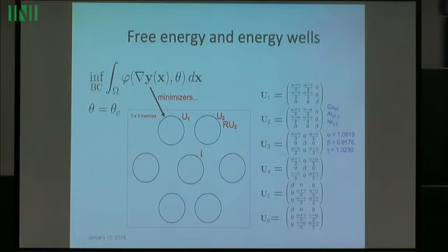And there's also rotational invariance, so that's what the circle denotes. So U2 in fact is also a minimizer, an equi-minimizer with the identity of phi, and the circle just represents all rotation matrices times U2. So it's a kind of copy of SO3. It's SO3 times U2. And this is SO3 times U1, this is SO3, and so forth. In this case, there's 6 of these martensite energy wells, and this is the austenite energy well. Everything's at the same height because we're at the transformation temperature. If we raise the temperature, these wells go up relative to this one. If we lower the temperature, these wells go down relative to this one. Typical first order phase transformation picture.